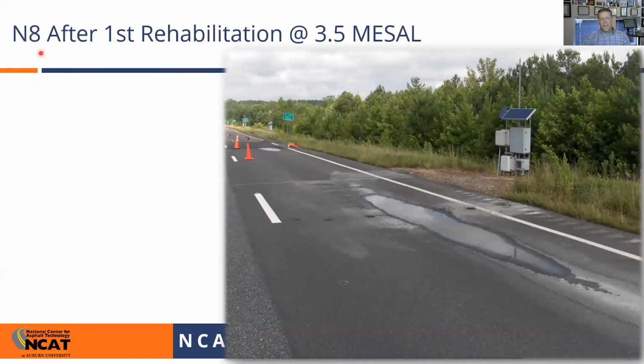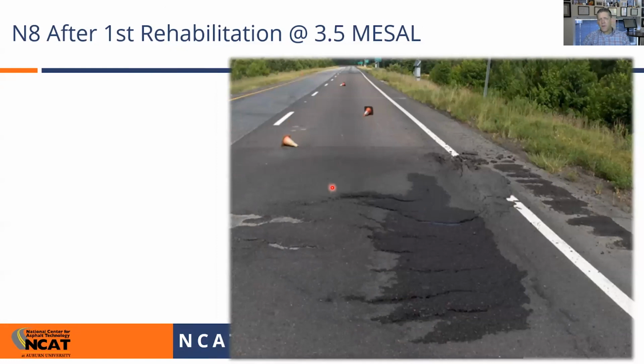This is section N8 after the first rehab at 3.5 million. So this is the conventional rehab, and you can see water standing in the wheel path from the extensive rutting. You can see other things going on. Whenever we've got cones out on a section, when we're under traffic, you know that it's a pretty severe situation where we don't want trucks traveling through here. Close up of that far end of the section there, the whole mat is kind of shoving off to the side. We're in a very serious situation in terms of being able to get this section to make it to the end of the test cycle.